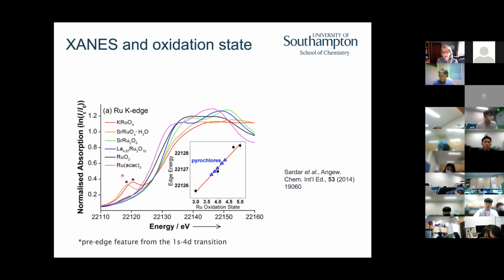Well, we can look at the oxidation state of the ruthenium from the XANES, and we do that by looking at the edge energy position. And we've made a series of reference compounds, right? So these are all of my reference materials. I know the oxidation state of the ruthenium in the reference materials, and that allows me to calibrate the edge energy to give me the oxidation states.